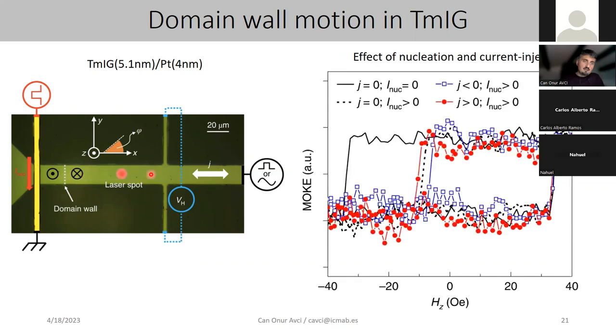So the first experiment that we do, we first just sweep the out-of-plane field and check that we get the normal symmetric coercivity. So that's basically when there's no current flowing along the track and no current flowing around the nucleation line. In this case, the solid black line, you see this coercivity is fully symmetric, about a bit more than 30 Oersteds.